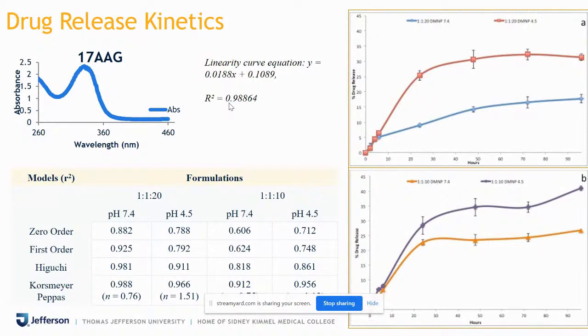So you can get a UV absorption maximum and create a linearity curve and release kinetics using it, along with your blank, of course. Using UV-visible spectroscopy and XPS, we were able to confirm that the drug was present in it, and using TEM and XPS, we were able to confirm the Fe was also present in it. Now the release kinetics showed us that the release was done.